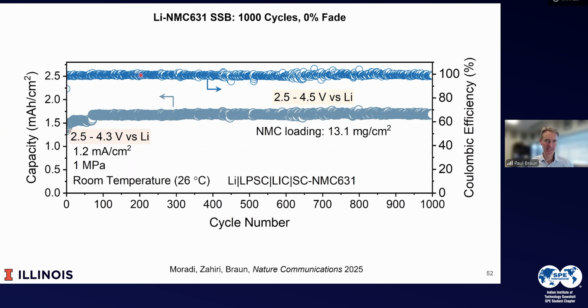And what we see here, this is sort of, I would say, our best cell to date. This is cycled to 4.5 volts, so very high voltage. And what we see here is that there is virtually no fade after 1,000 cycles in a solid state at 1 MPa. And that's very significant because that means that you can start thinking about a practical system. This is made with the NMC versus LIC. We have not combined this with some of the other approaches to improve the batteries. And so I think we'll get even better performance over time.